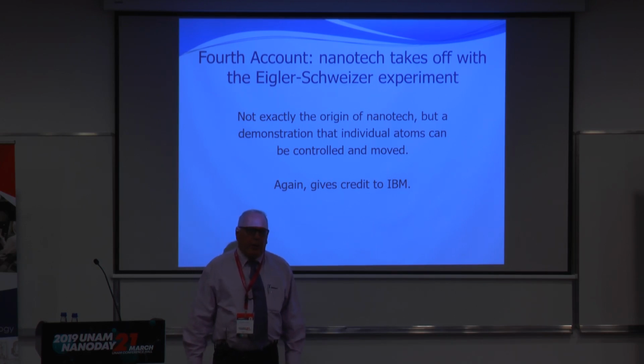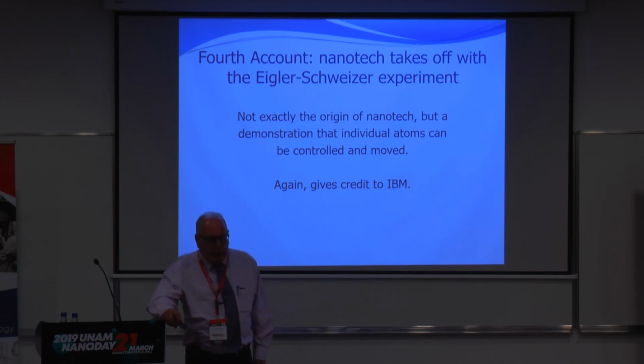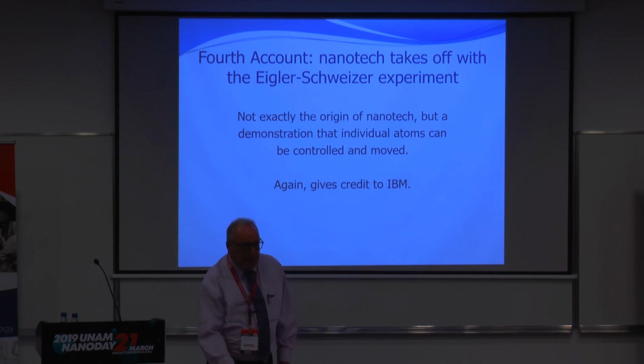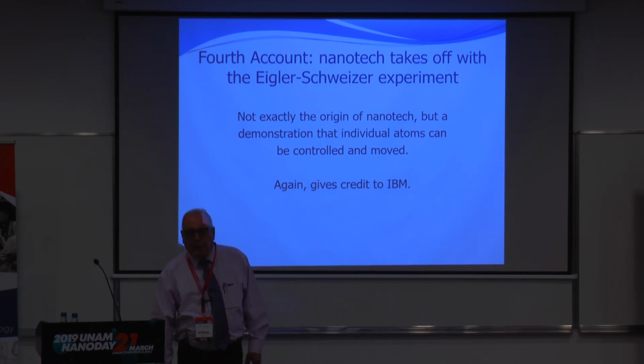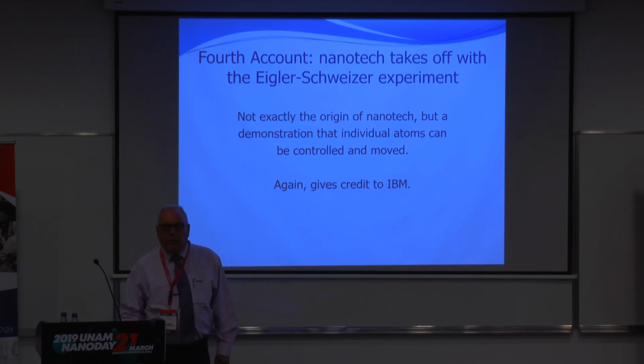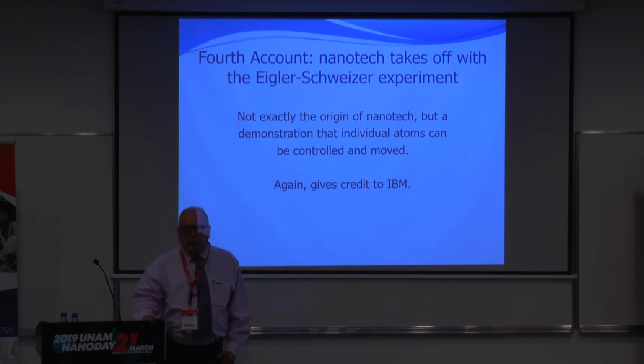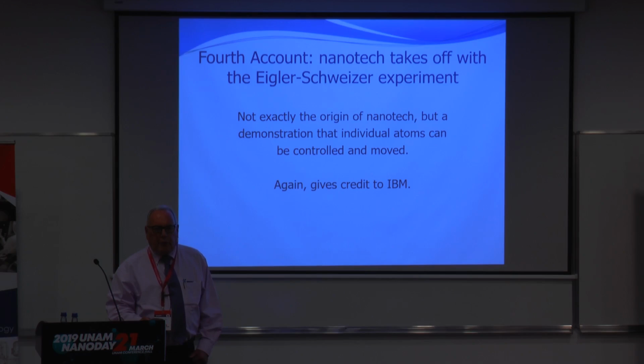And then there's another story which also comes out of IBM, which is that nanotech takes off with the Eigler-Schweizer experiment. And you may or may not be familiar with this, but in November of 1989, Donald Eigler and Erhard Schweizer were working at IBM Almaden in San Jose, California. And they used the chamber of their STM to, first of all, get their high vacuum and their extremely low temperature, 4 degrees Kelvin. And they had a nickel surface, and they sputtered xenon atoms onto the nickel surface.